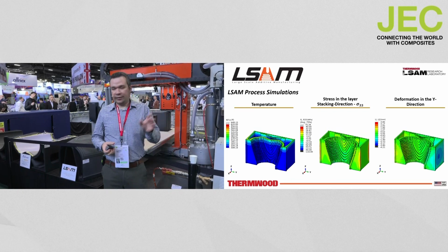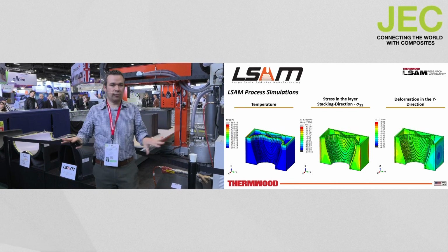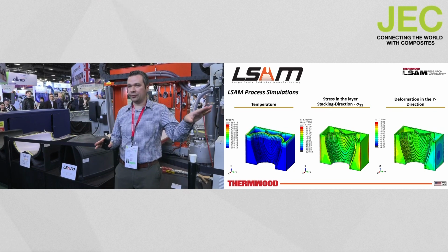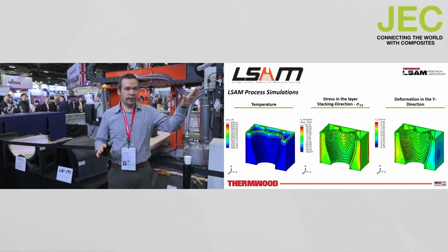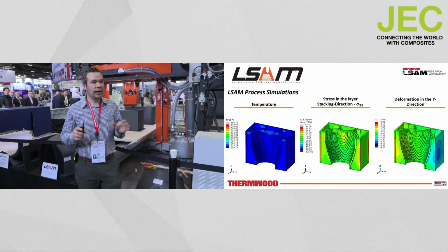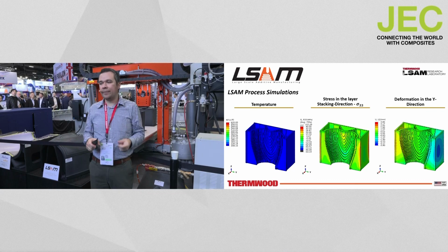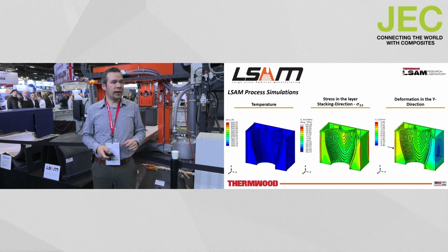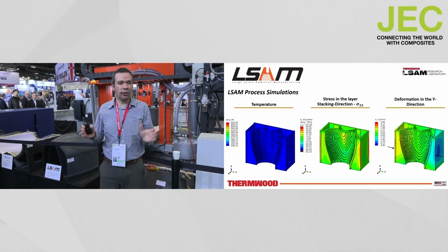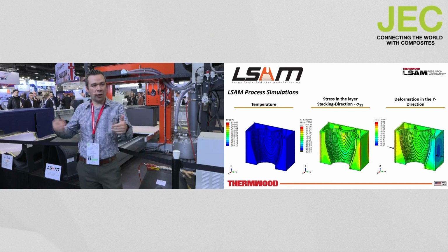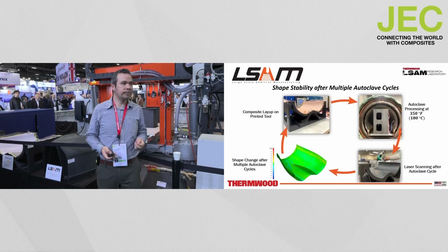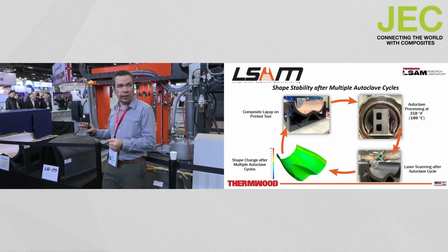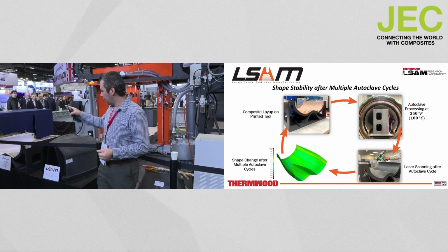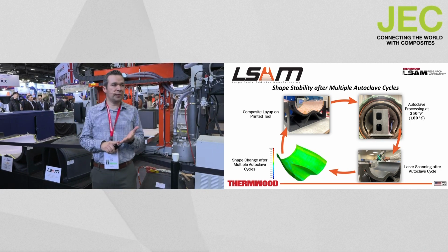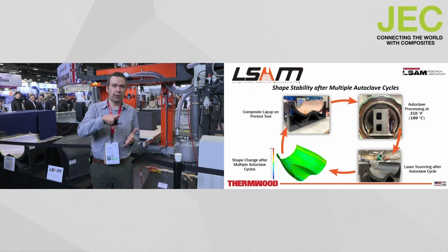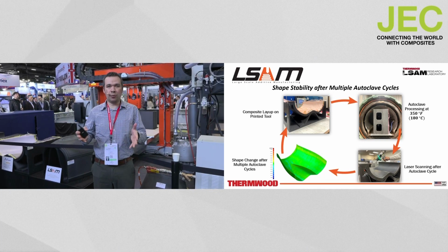Similar to traditional laminated composites, this is an anisotropic material. So there are stresses that arise from not only the temperature gradients, but also from the anisotropy of the material. And some of those stresses also lead to spring back, or spring in in this case, as you can see here, for this geometry actually sprung in on the ends. So the geometry that we are printing is compensated to account for that spring in. As Scott mentioned briefly, we did a full study on these sets of tools where we look at shape and stability, and we did multiple autoclave cycles, where basically a layup was made on the tool.